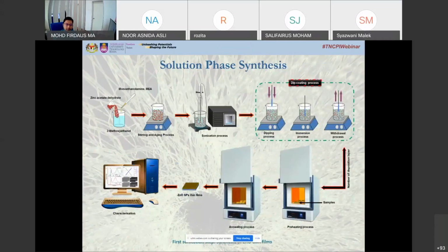And then finally, the last method that I want to discuss with you is the solution phase method. This method is generally carried out in a solution, and in this case we are using a water base. Whenever it is carried out in an aqueous solution, it is called the hydrothermal growth method, the alternative name that is widely used. But before that, a few layers of zinc oxide nanoparticles are seeded on the substrate, and the seeded particles promote nucleation for nanowire growth.